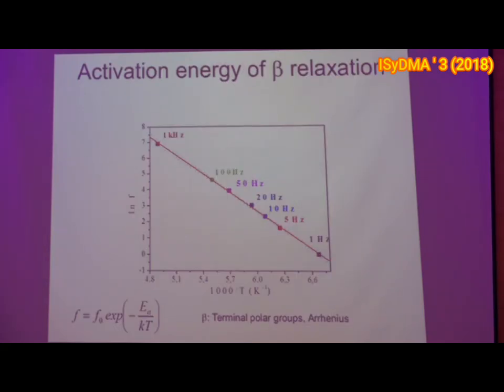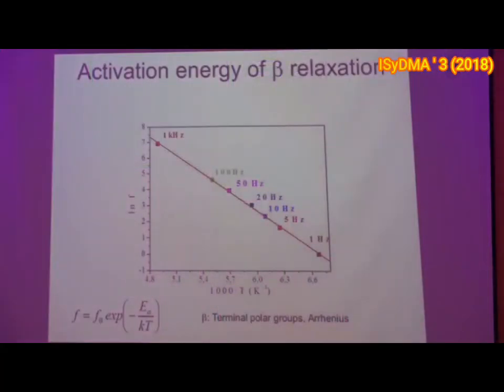Then we calculate these peaks, okay, and then we can use, for example, an Arrhenius law, and we say that this relaxation frequency is proportional to the exponential of this activation energy. And so if you put this in a logarithmic scale, this is a straight line with a slope that is proportional to the activation energy. So we can see that this is exactly a straight line.